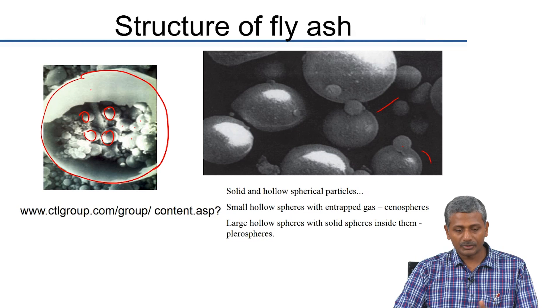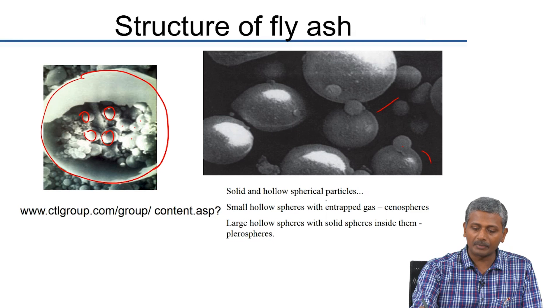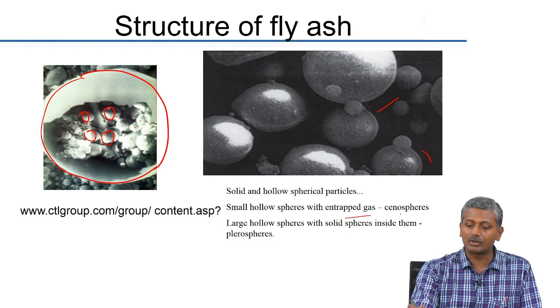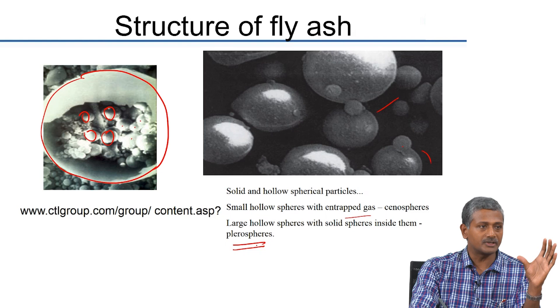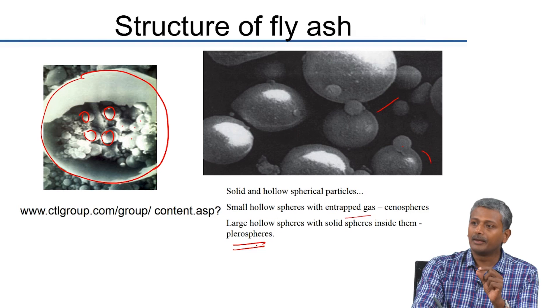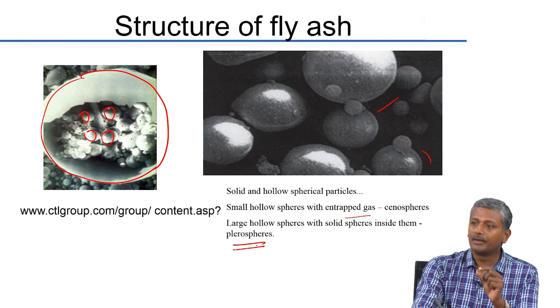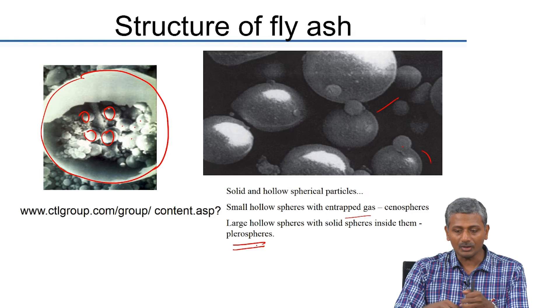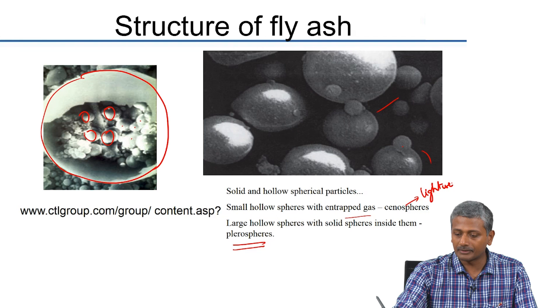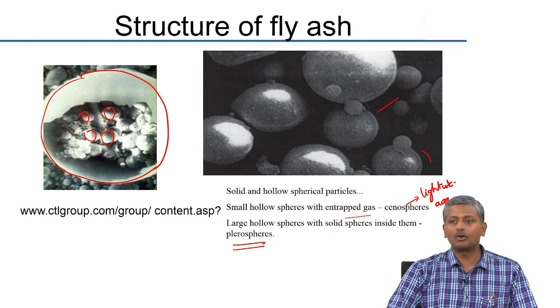There are several classifications for the type of particles. Solid and hollow spherical particles are seen in SEM images. Small hollow spheres with entrapped gas are called cenospheres, while large hollow spheres are called plerospheres. The large hollow spheres contain solid silica spheres which are essentially the reactive fly ash particles. Many companies that supply fly ash are now trying to collect cenospheres separately because they can be sold as a lightweight aggregate — obviously, being hollow, they are light in weight.